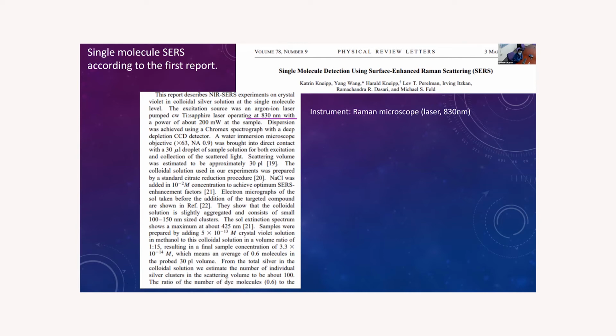Why are they using a wavelength in the near infrared? Well, perhaps it's because they want to measure single molecules, so the signal should be very small, and they are trying to avoid all the background that could be possible. For example, the fluorescence of the analyte molecule, or the fluorescence of other species in the solution. If we pay attention to the optics, they are using an objective of very high numerical aperture, and they said that the scattering volume is about 30 picoliters. I have already calculated that, and it's more or less, if we assume a box or a sphere, around 30 micrometers in diameter of the scattering region.